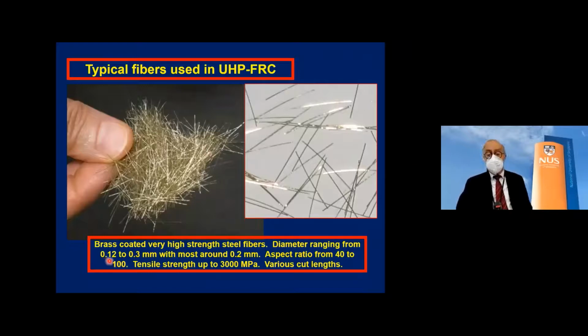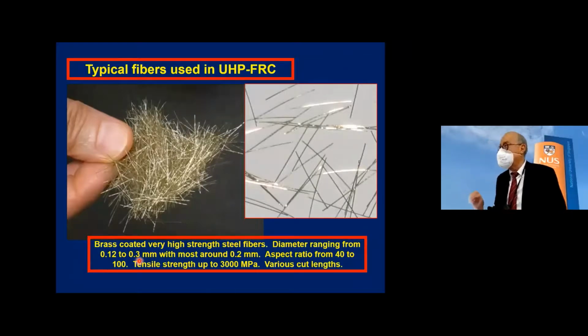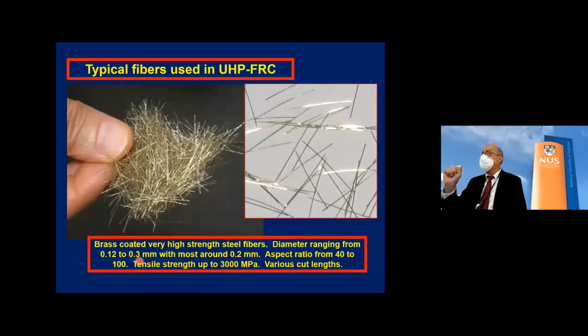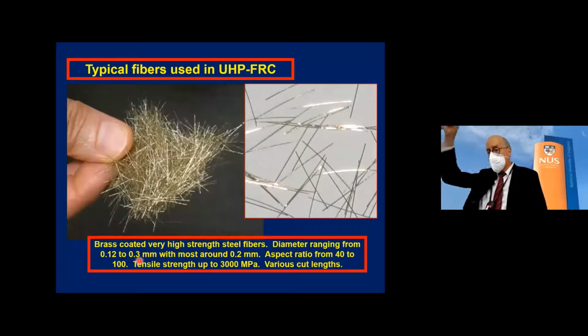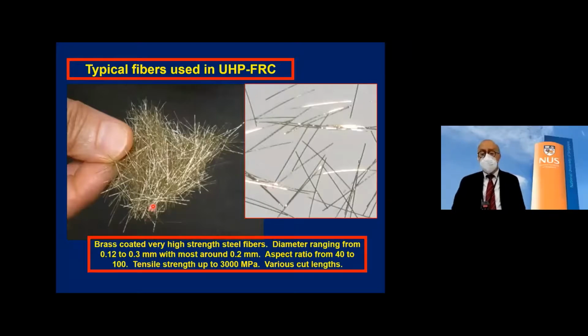They have a small diameter, 0.12 to 0.3 millimeter. You know, in producing steel fibers, when you go to small diameter, it is very expensive because you have to draw the fiber through different dies. It's not like a glass fiber, you let it flow and it becomes smaller and smaller diameter. So for ultra high performance concrete, we have fibers with relatively small diameter, aspect ratio that is length over diameter in the range 40 to 100, tensile strength up to 3,000 megapascal. So I just mentioned this to make sure that when we talk about fiber, ultra high performance concrete, it's not just a run of the mill fiber that you would use.